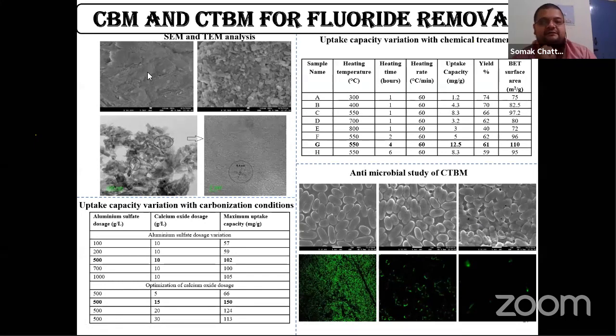Now, coming from the SEM and the TEM analysis, this represents a merely clean, amorphous structure, whereas after treatment there are deposits of aluminum and calcium over its surface. And from the transmission electron microscopic structure, we were able to see aluminum rod-like structures inside the pores of chemically treated carbonized bone meal. And based upon the lattice fringes that we obtained, we were able to say that we had a good scope of impregnation within the material.